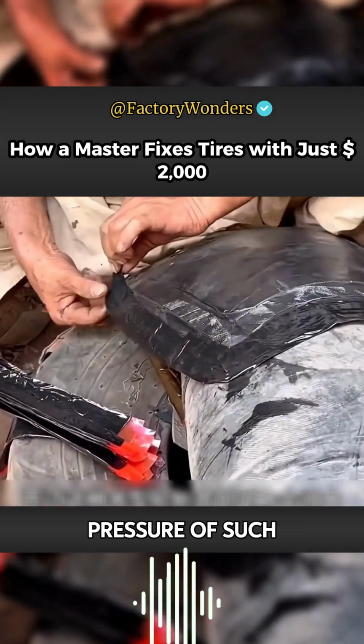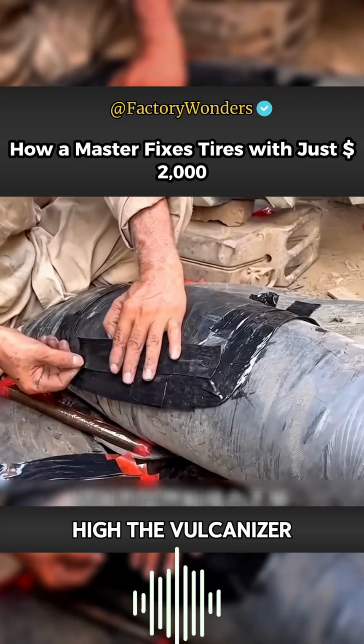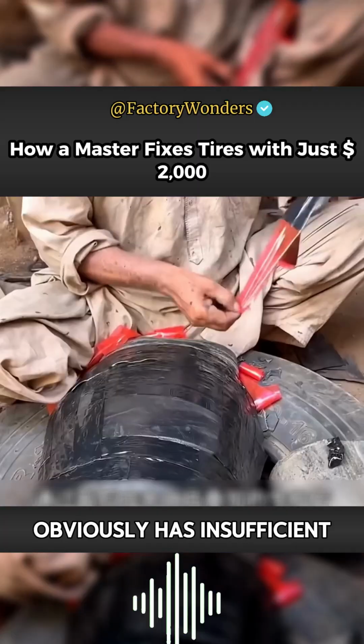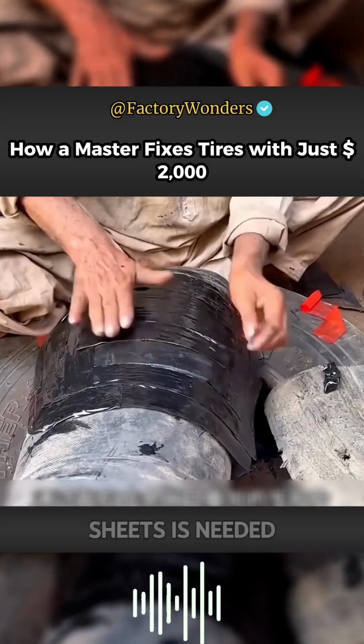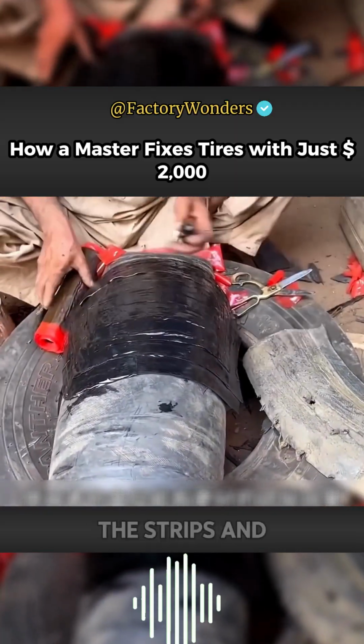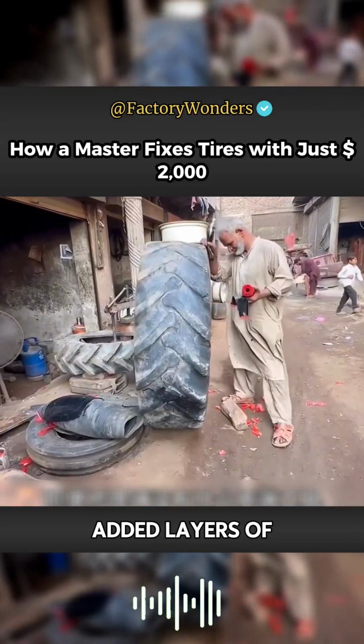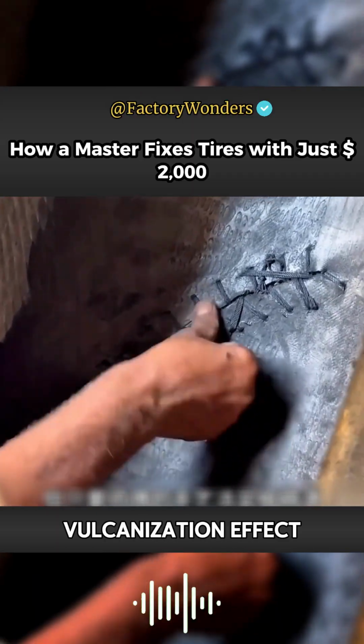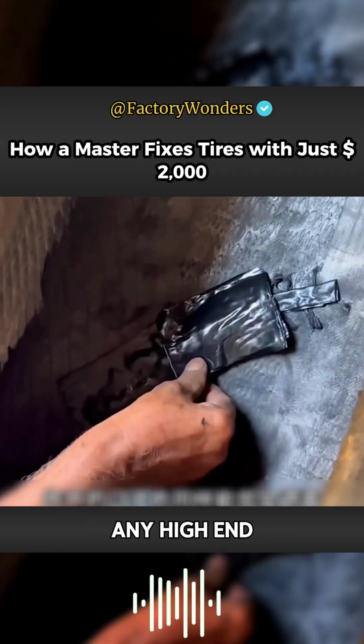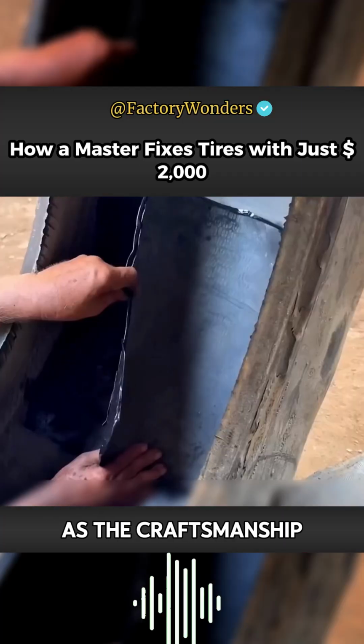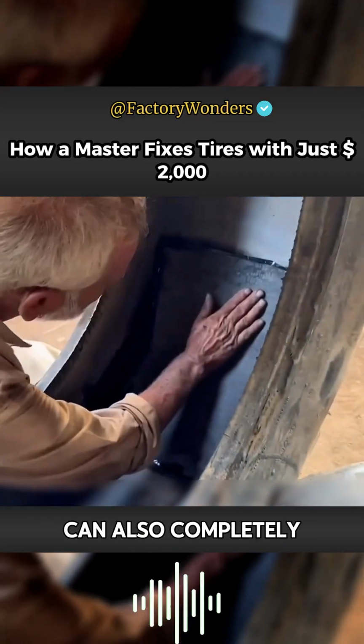However, the internal pressure of such a large tire will be very high. The vulcanizer obviously has insufficient bonding strength, so a layer of raw rubber sheets is needed. The raw rubber sheets cut into strips and stacked together can make the added layers of the two have a better vulcanization effect. The repair shop does not have any high-end tools, but as long as the craftsmanship of the master is exquisite enough, it can also completely cover.